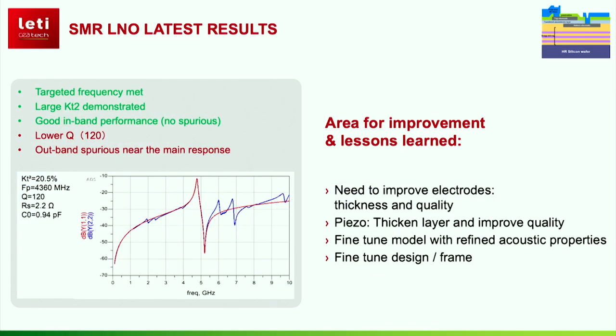Now, let's look at the electrical result for the SMR. The red curve here is the simulated response using a Mason model, and the blue curve is the measured response of the resonator. The coupling coefficient that is calculated using the resonant and anti-resonant frequency is quite good. The resonators show no spurious in-band, but quite a bit out-of-band. Furthermore, the quality factor is still lagging, namely because the electrode thickness and deposition quality need to be improved. Despite that, these are very encouraging achievements at such high frequency.